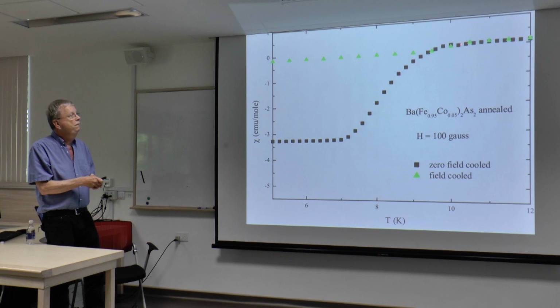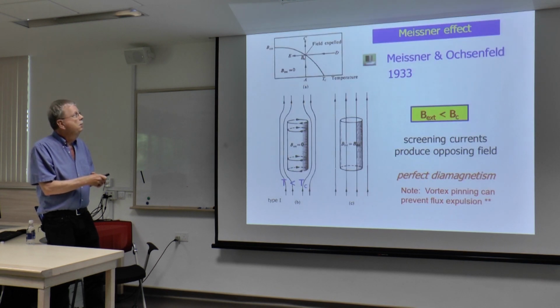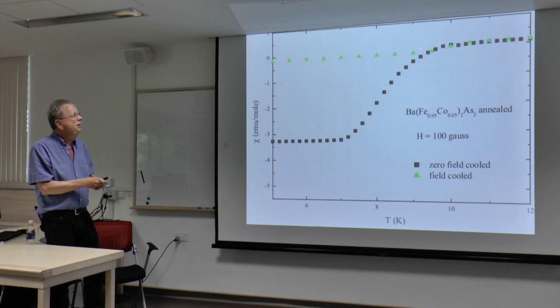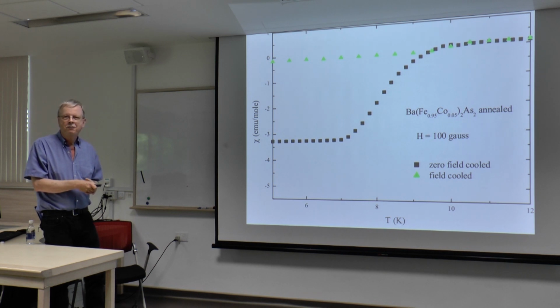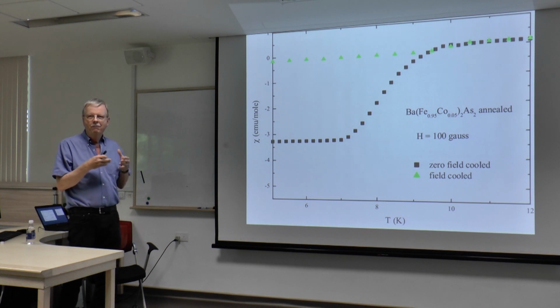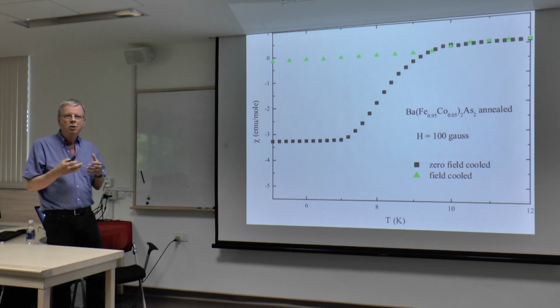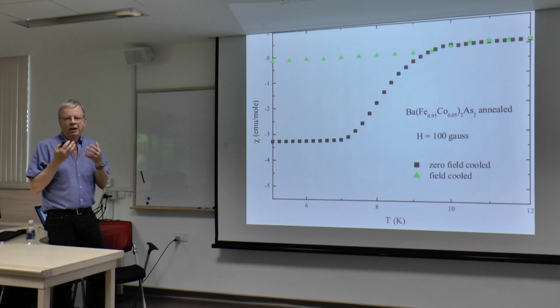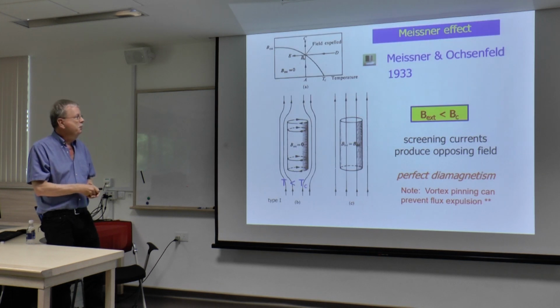However, if you cooled in field, which would be the line that was shown to you here, you get this little teeny tiny amount of flux expulsion. I think you can see it. And that's what the Meissner-Ochsenfeld data for tin show. If you can read German, you can go read it for yourselves. It's not total flux expulsion, only in lead, where there was no flux pinning. And the flux lines in this picture get pinned to impurities, and it's a big study.